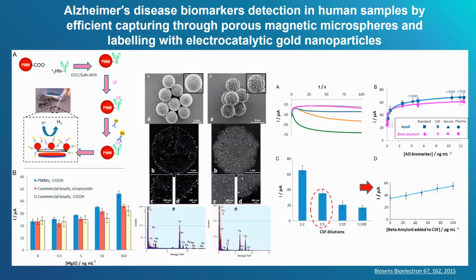So this is one of the first examples of electrochemical sensors we have been working on. This was for Alzheimer's disease biomarker detection in human samples, again a collaboration with the hospital in Barcelona, in which we used polymeric particles that were modified with antibodies against the biomarker we wanted to detect, in this case for Alzheimer's disease, and of course a secondary antibody that was modified with gold particles. By using the hydrogen evolution reaction catalyzed by gold nanoparticles and using a magnetoelectrode, we were able to measure this hydrogen evolution reaction and quantify the current produced during this process, and correlate this current with the quantity of gold nanoparticles, which is related to the quantity of the biomarker we want to detect.